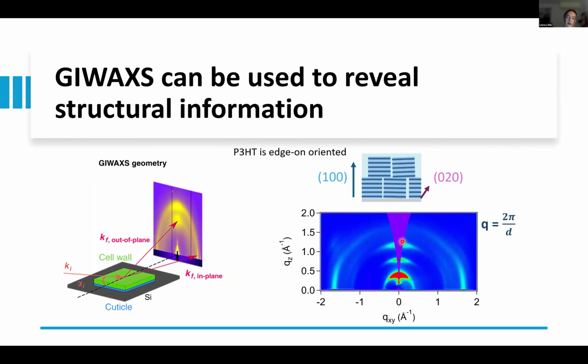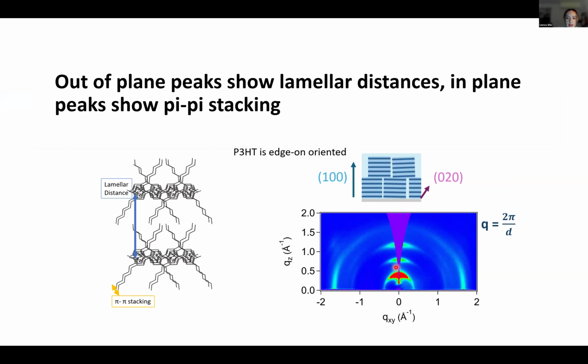Okay, so I mentioned earlier about the crystal structure of P3HT, and we can observe that using this technique called grazing incidence wide angle X-ray diffraction, or GIWAXS. So here we're sending X-rays over the film, and at angles where we have constructive interference, we get some intensity on the plot here. So P3HT is edge-on oriented, meaning that these peaks here correspond to the lamellar distance between the side chains. And this is actually where anions intercalate. So we are expecting that this distance is going to increase with the intercalation of anions.